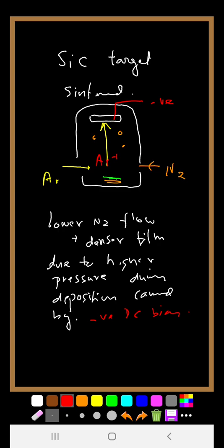The average hardness and modulus of the SiCN coatings were 21 gigapascal, this is for the hardness, and 200 gigapascal, this is for the modulus. It's an average value, but there may be slight alterations. And these values were obtained by nano indentation. This is specifically used for film property, mechanical property determination.